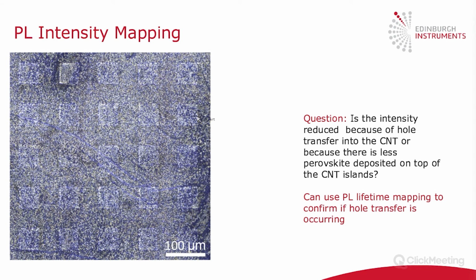So if we look back here to the dark field image, one question that might arise is, how can we be sure that this difference in PL intensity we saw is due to hole extraction and not simply due to the amount of perovskite sitting on top of the carbon nanotubes? You could argue that the way perovskite deposits onto the ITO and the carbon nanotubes is different, and you might have less perovskite here, and this might be responsible for the photoluminescence decrease. So we would really like a complementary measurement technique to confirm this hypothesis that it's due to hole extraction. And the answer is to use photoluminescence lifetime imaging to do this.